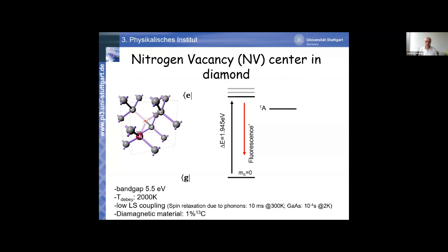On the one hand, all lattice vibrations occur at very high temperature, and characteristic for that is what we call the Debye temperature. This is a measure for the cutoff frequency of optical phonons, and this is 2000 Kelvin, which essentially means that below these temperatures, a lot of optical phonons, that is short wavelength lattice vibrations, are non-existent. And that in turn means that as phonons are the number one scatterers responsible for decoherence of all optical transitions, but also all spin transitions, these decoherence mechanisms are not very prominent, even at elevated temperatures like room temperature.